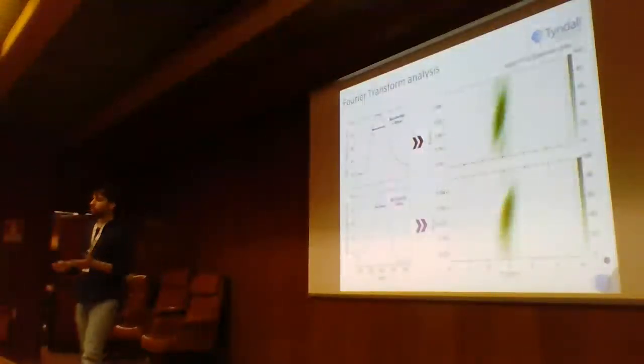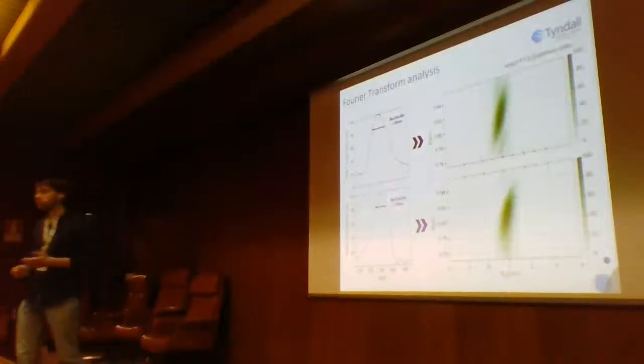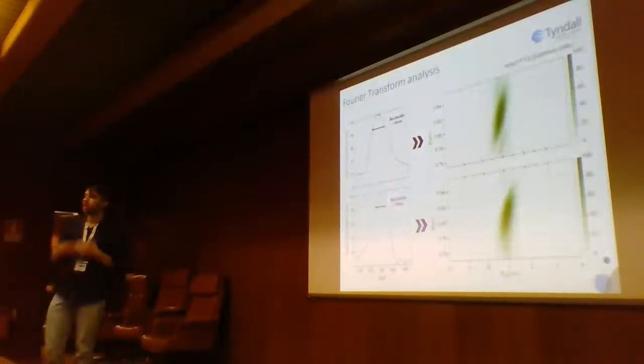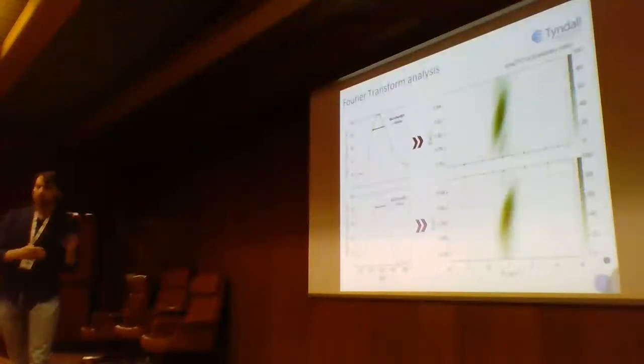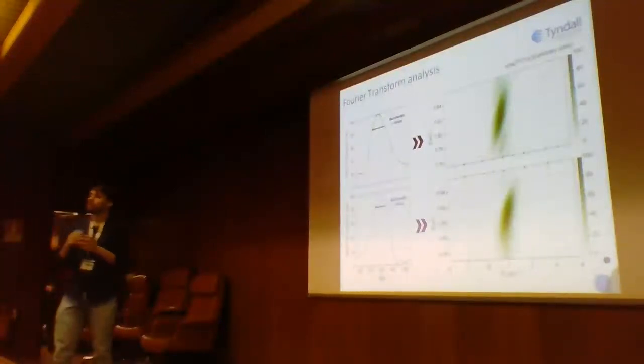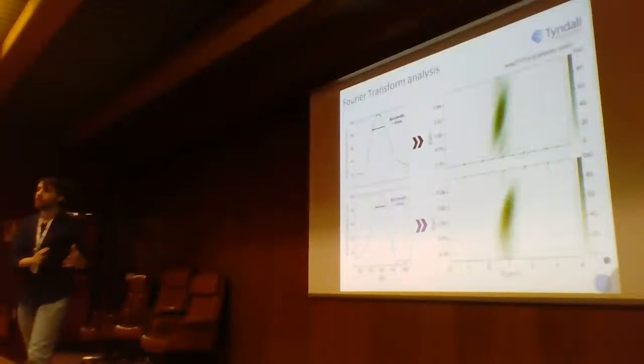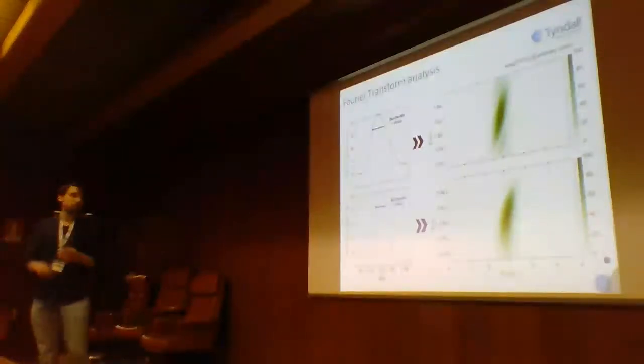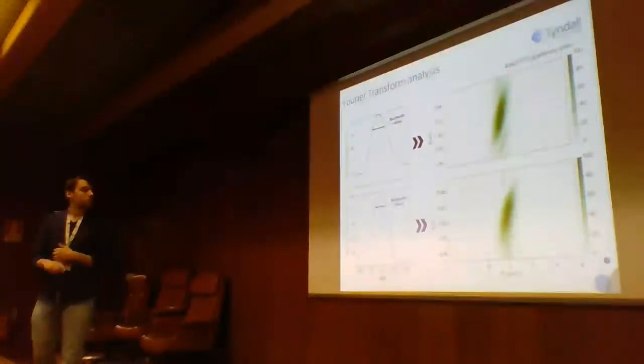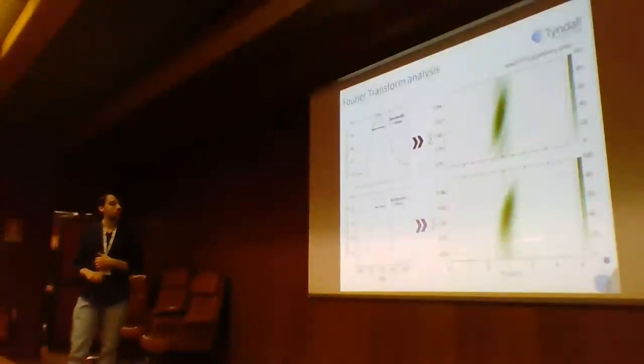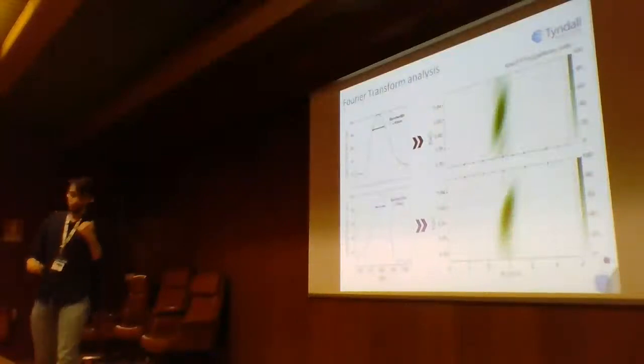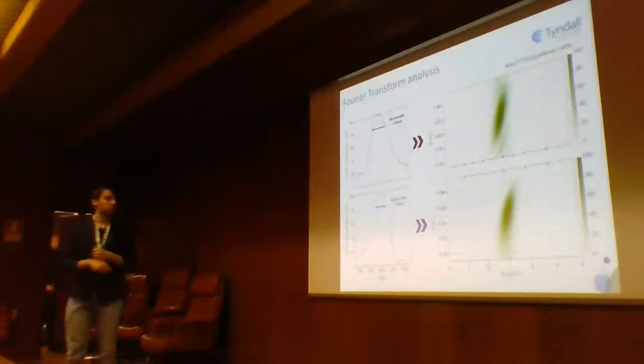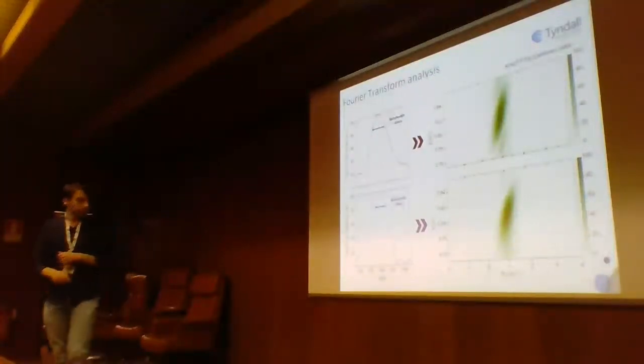To have a general and better overview of this problem, what we can do is to take also the Fourier transform of our source, in this case the fiber, and to get the overlap region between the Fourier transform of the grating coupler and the Fourier transform of our source. As you can see, again, we get a uniform image for the uniform grating coupler that is spreading in terms of the energy, while in the case of the non-uniform grating coupler, we have a blurry region here that is close to the thicker part that I've already shown you in the previous slide. And in terms of the energy, the spreading is smaller.